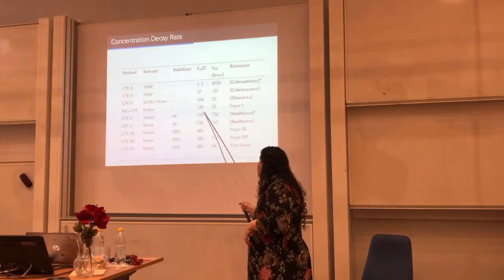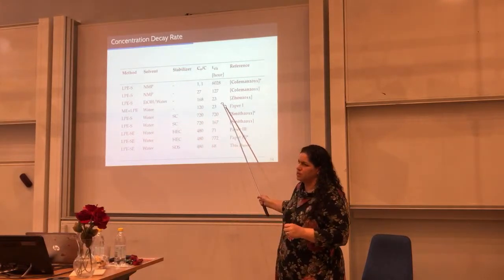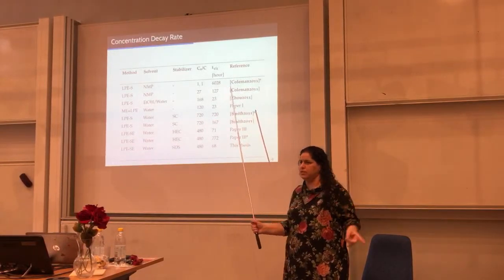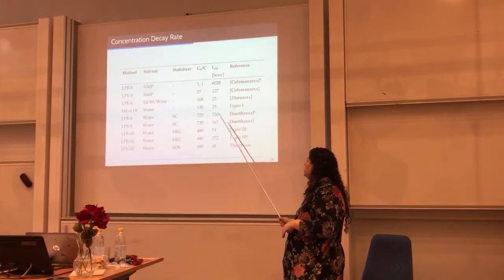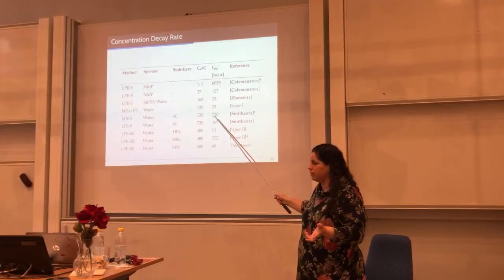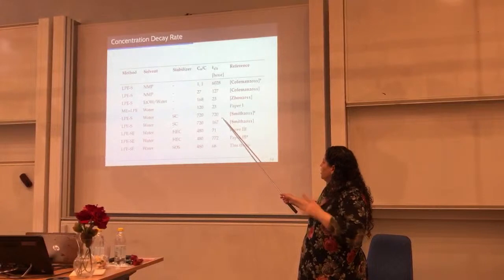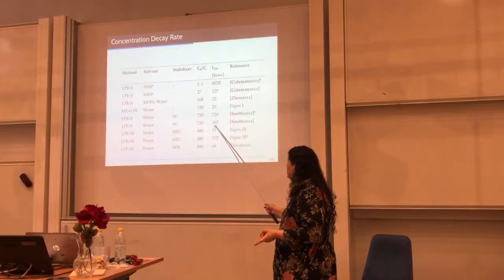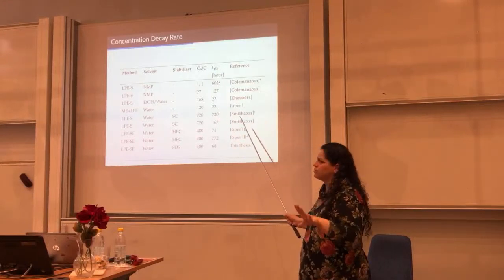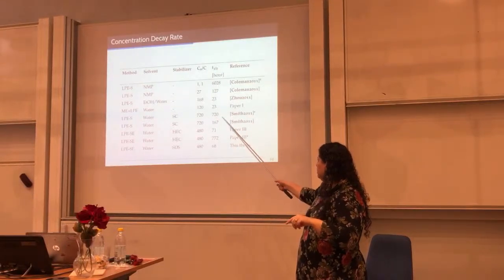So in our work in water, we had about 23 hours for these dispersions to reach half the concentration they had when we started the experiment. When you use sodium cholate, that's another surfactant, in a very famous work also from Coleman's group, they achieve 167 hours or 720, depending on the initial concentration that I took to do the calculation.